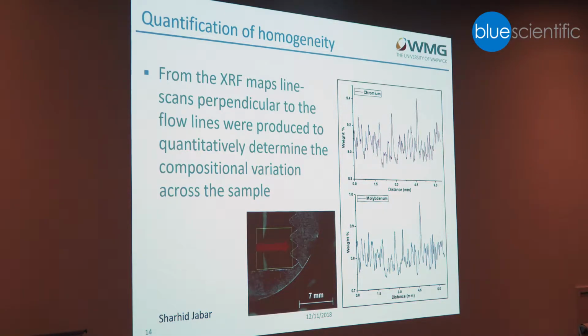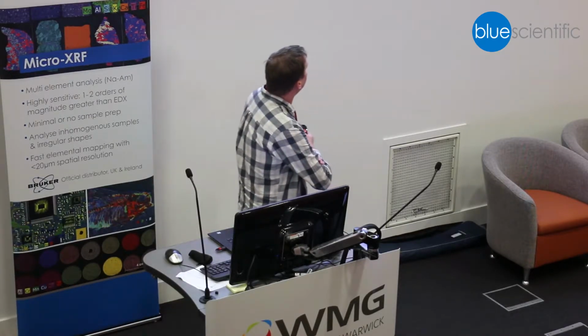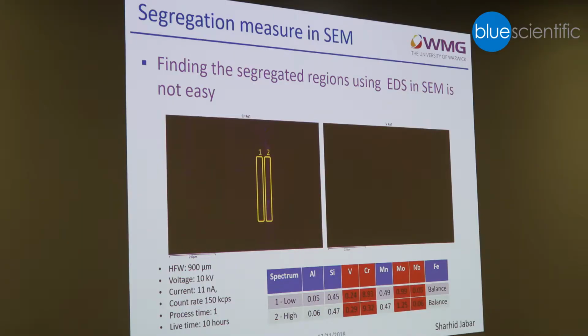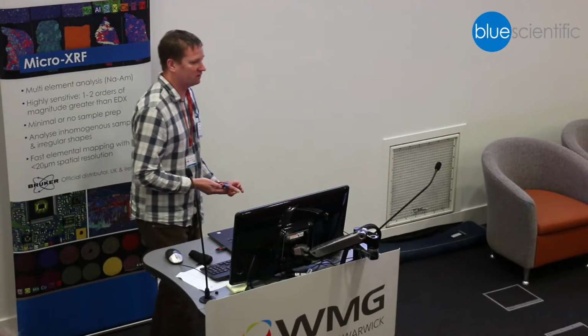And as we can see here, there's significant molybdenum segregation in these flow lines. We can quantify the compositional change within these lines just from the map data, and then we can go into an SEM and try and find the same segregation behaviour in an EDS map. And we found this really difficult, even when we were collecting under very aggressive conditions, 150,000 counts per second for 10 hours, we can only just about see the segregation lines in an EDS map. And I think that's because the sensitivity of XRF is higher when you think about how you're averaging a larger volume with each pixel, whereas in the SEM you get a lot more noise because you're looking at small features.